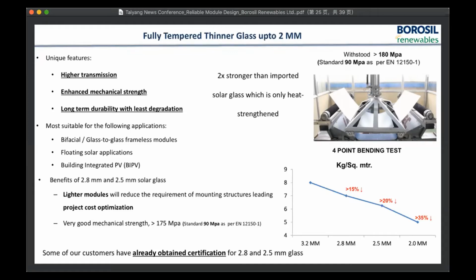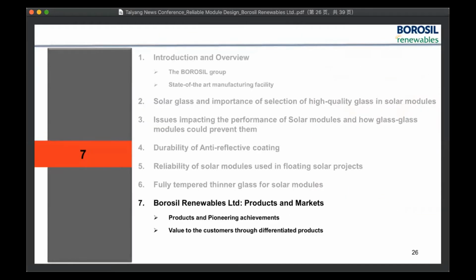So the graph tells you that with the 2.8 mm thinner glass, the module weight reduces by 15%. With 2.5, it reduces by 20%, and with 2 mm thinner glass, the module weight reduces by 35%. So that's how the module weight could also be optimized using the thinner glass, which also will bring down the requirement of the structural design. So the project cost could also be optimized that way. So it has got a positive impact on LCOE as long as it meets the basic safety requirements of the project. Next slide, please.